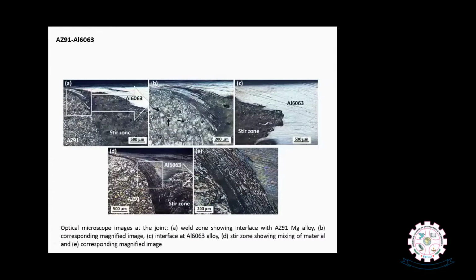And the cross section of the successful weld joint also indicated the mechanical mixing of materials from both AZ91 and aluminum alloy. Unlike in similar magnesium alloys, here the metallurgical continuity was poor. In the majority of the area, you can see the mechanical mixing of both aluminum and magnesium base alloys in the stir zone, which actually helped us to form a strong bonding.